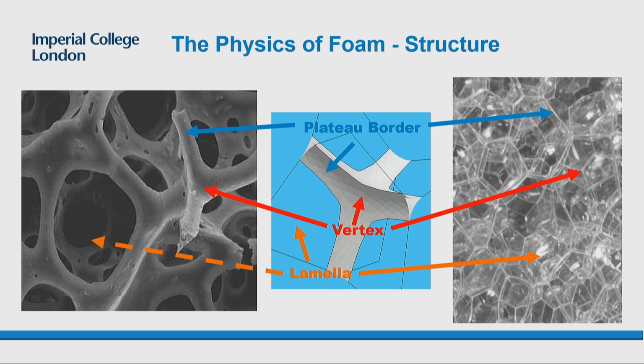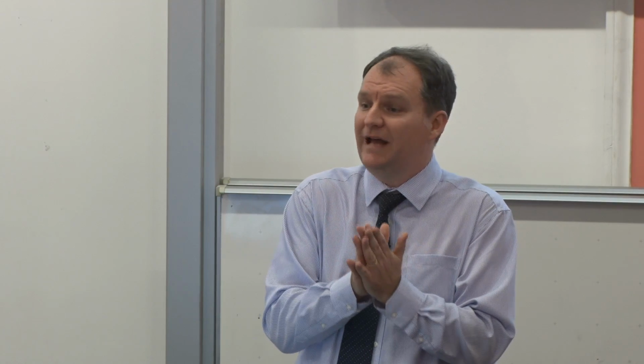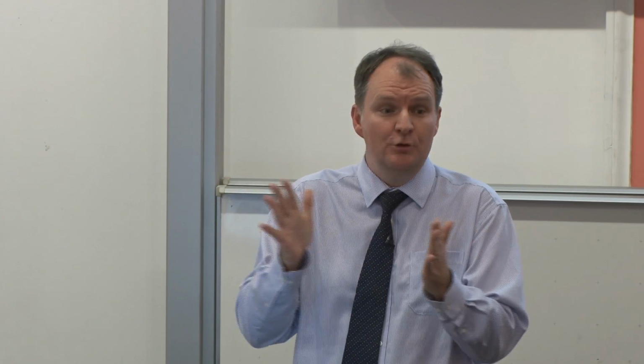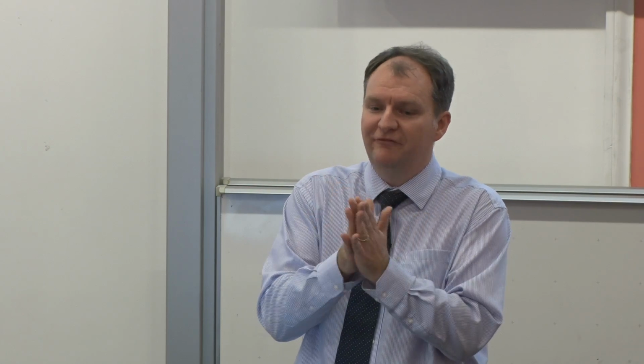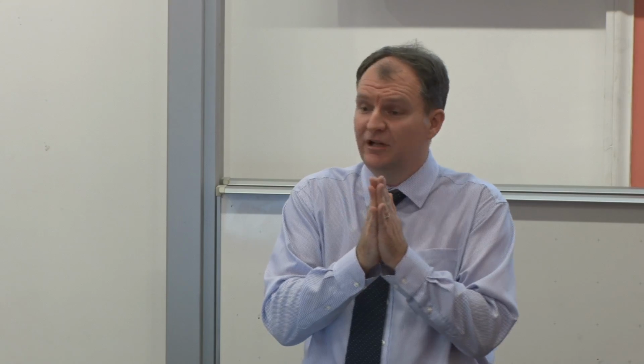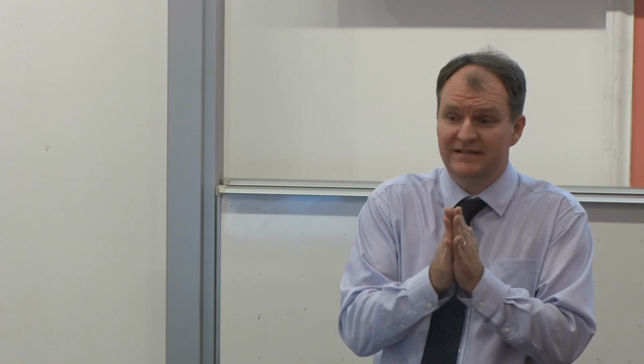And these plateau borders have a curvature inward. So if you look at them, they curve inwards, which means that because they've got a surface tension there, the pressure in the bubble will be higher than the pressure in the liquid inside these plateau borders. This means these plateau borders actually exert a suction on the liquid in the films. They actually try and suck the liquid out of the films, and these films only stop thinning when the forces between the two sides of the film are high enough to actually oppose the suction force.